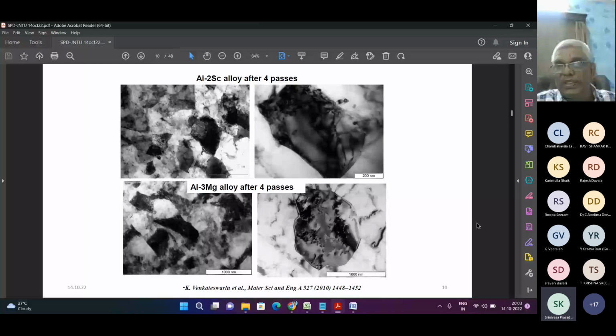The optimum size you can get is 20 nanometers, so people have restricted to that. Beyond this size, even if you reduce the grain size, there is no effect. This was the work carried out by Professor Atul Chokshi, who is one of the key members at IISc Bangalore on severe plastic deformation, and who worked with Professor Terence Langdon in the USA, where he did his PhD on nanostructured and ultrafine grain materials. This is one case where we have done that extensive TEM work. Next slide, please.